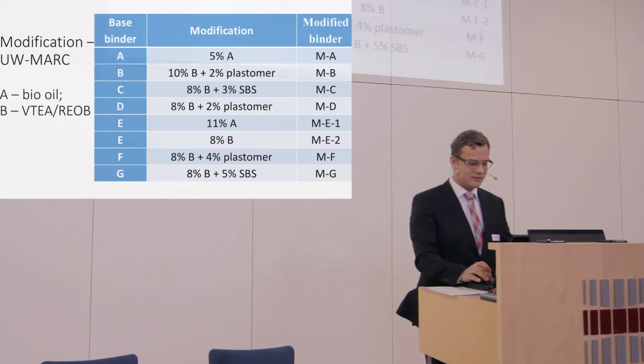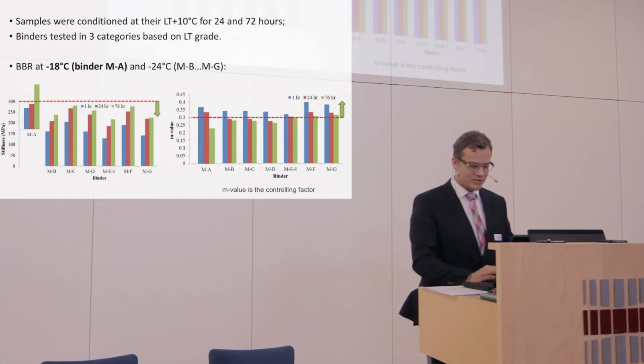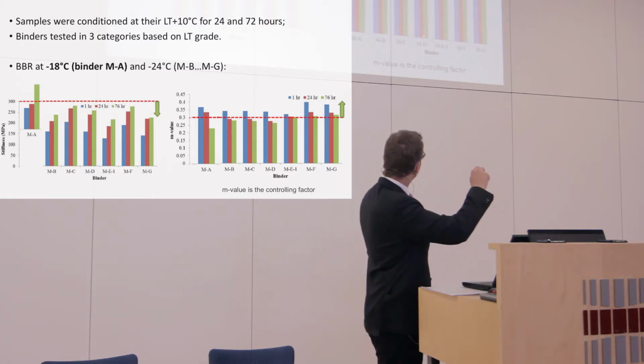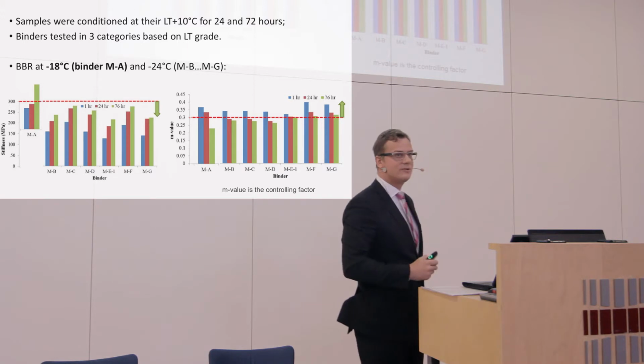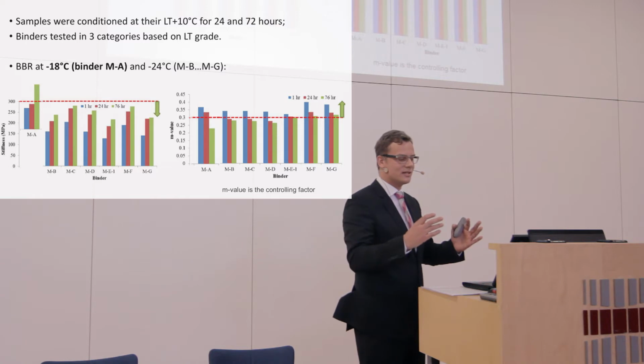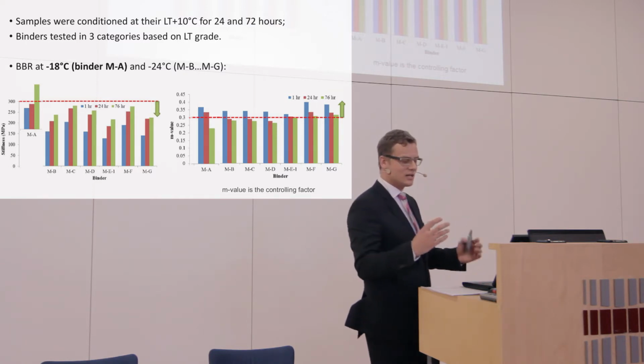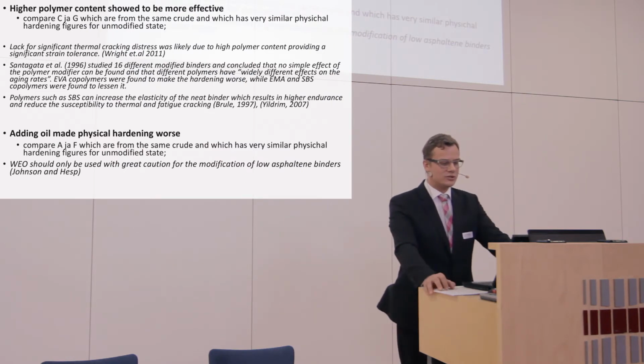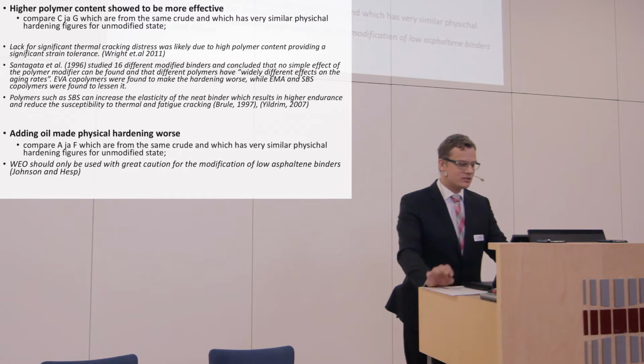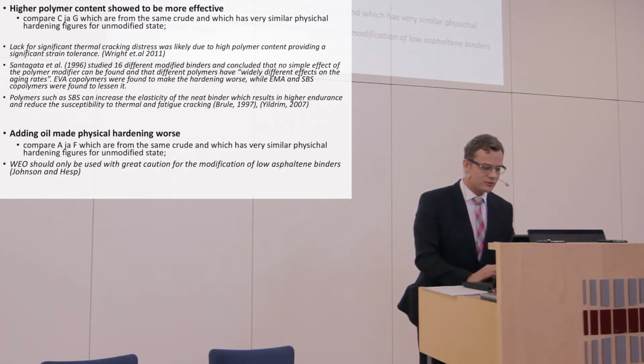Going back to modification, for C and G there's the same amount of oil, but for C there's 3% of SBS, and for G there's 5% of SBS. So for G, there's more polymer inside it. Looking at the results, C does not fulfill physical hardening requirements, but G fulfills physical hardening requirements. Of course, there's a slight difference: C is penetration 70/100 and G is penetration 160 to 220. But we can validate this conclusion with support of literature.